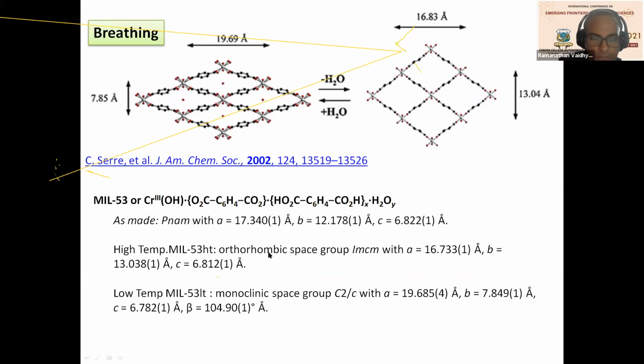And then there is an intermediate phase, which is neither the parent nor the high temperature phase, but a low temperature phase, which is a completely different structure, monoclinic, with entirely different lattice parameters. So single crystal X-ray diffraction, or sometimes powder X-ray diffraction, is a nice way to follow these types of structural changes. But the most important thing is we are going to be talking about structural change caused by a gas, whereas this is a structural change caused by desolvation assisted by temperature. But the type of structural change is breathing of a MOF.